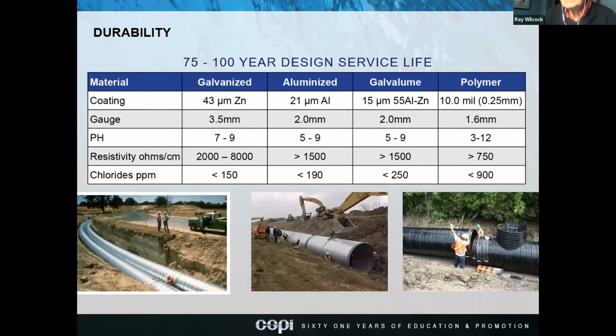which is basically seawater. I've tested water, and like brackish water, which is a combination of seawater and fresh water, you're talking about 700 to 800 parts per million. So you're getting up into the seawater areas. Okay. And there's a few pictures: you have galvanized here, you have aluminized here in the middle, and you have polymer laminated spiral rib pipe over here.